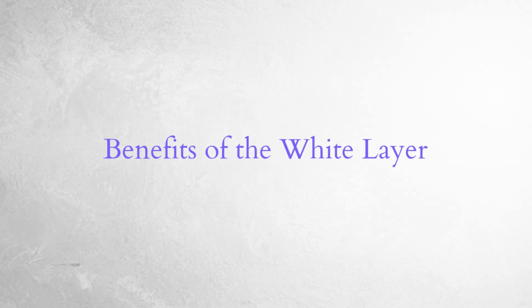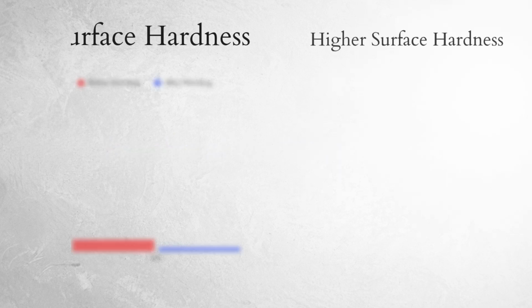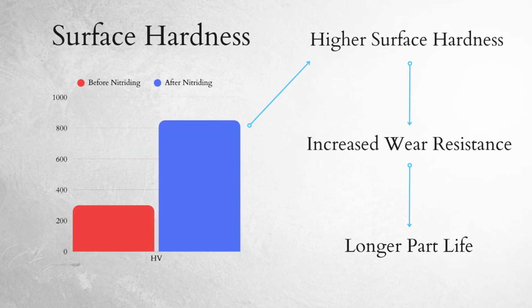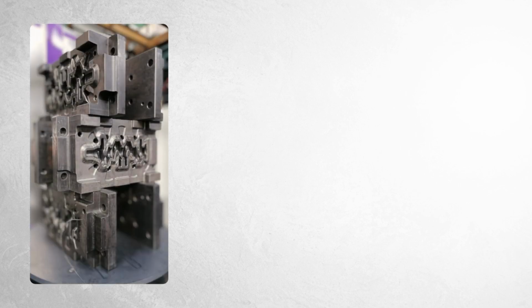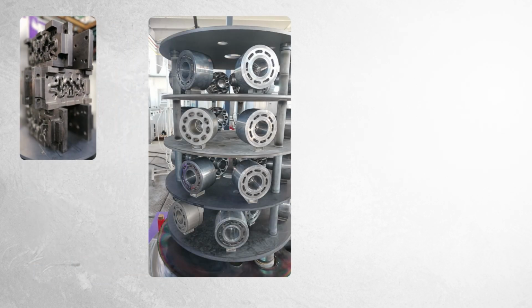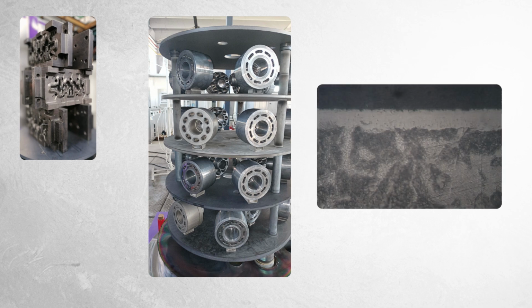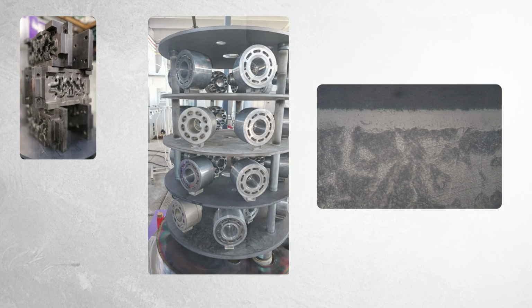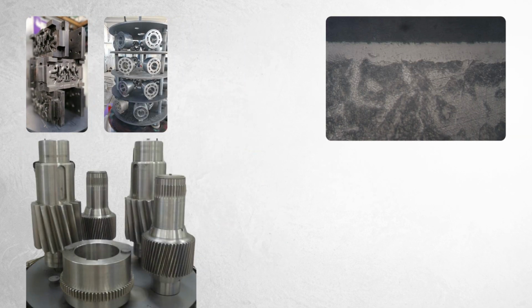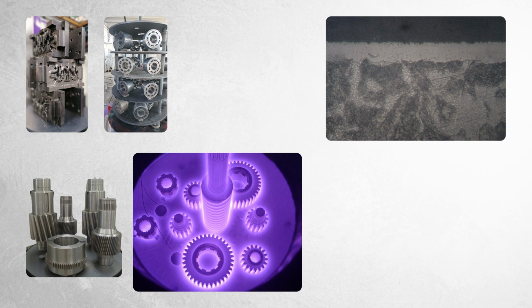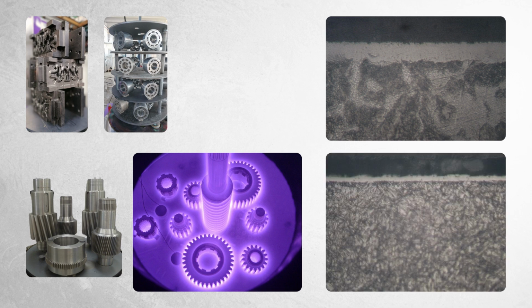A compound layer can be very useful because it has high hardness and can improve abrasive and adhesive wear resistance, and often corrosion resistance. However, not every part needs the same nitrided structure. For components such as dies, molds, and some hydraulic parts, a controlled compound layer, often rich in epsilon iron nitride, can be beneficial. While for parts exposed to high contact stress or fatigue loading, such as gears and shafts, the compound layer is usually kept very thin and dense, or sometimes avoided altogether.